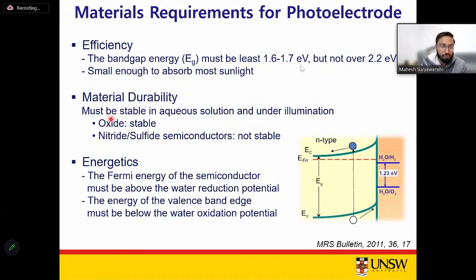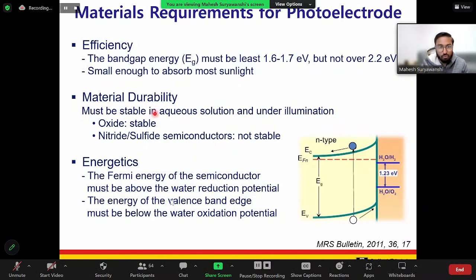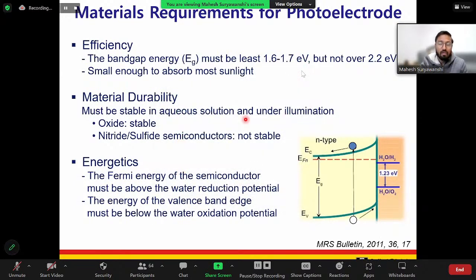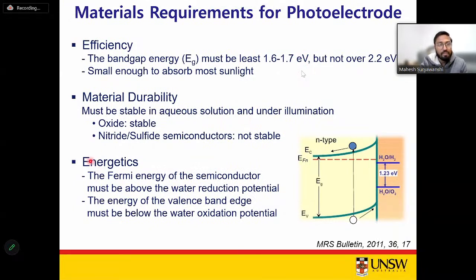Second one is materials durability. Because we prepare this material and directly immerse it in alkaline, water-based solutions, it should be very, very stable in this solution, and also under illumination, because we have to shine a light for the water splitting reactions to happen. So these two requirements should be met at the same time to have an efficient water splitting reaction.